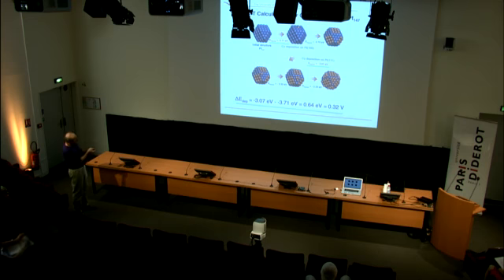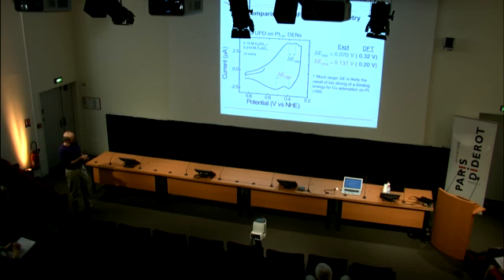Now we're correlating these two peaks in the cyclic voltammogram to these two energies. We just subtract these two energies. That's 0.64 eV. You have to divide by 2 because there are 2 electrons, to get volts: 0.32 volts. So this is the voltammogram that we're correlating to, and we're looking at these two peaks right here. We call this delta E deposition. Well, what we measure is 0.070.